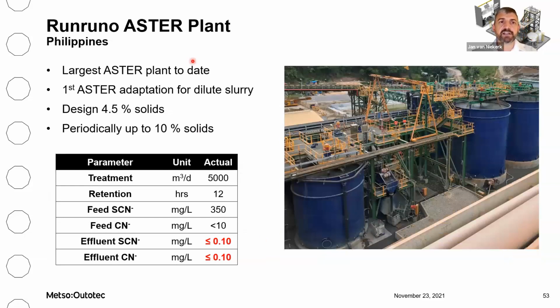The third application was the Runruno plant in the Philippines, and this is by far the largest aster plant to date. This is also the first plant where we had to treat a dilute slurry. This is because of the requirement for Runruno to detoxify the solution prior to discharge onto the tailings dam. So as you can see on this graph, you've got your standard CIL, followed by a cyanide detox step using standard SO2 air.